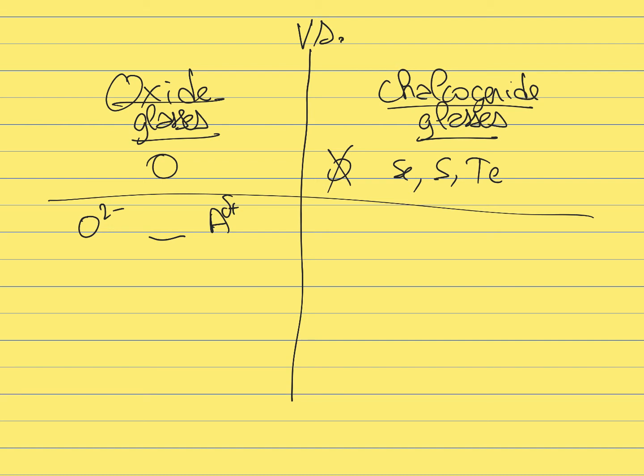In the case of Chalcogenide glasses, when you have those selenium, germanium, arsenic, etc., those are going to be neutral elements. Those Chalcogenide glasses tend to form covalent bonds, and in covalent bonds, the electrons are shared between the two atoms. The electrons are just delocalized between the two atoms. So in this case, each of those atoms will be neutral. There won't be an excess of negative charge on the oxygen and a deficit of negative charge on the cation. All those atoms will simply keep their charges and remain neutral.